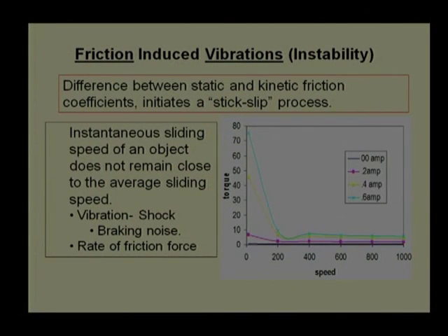To elaborate on this, I am showing a couple of results from experiments we have done on one brake material. We used a magnetorheological liquid as the brake material. The good thing about MR fluid is that it gets solidified in just a few milliseconds, and due to this solidification the coefficient of friction increases significantly. The coefficient of friction can go from 0.1 to 0.6 in 10 milliseconds, which gives a braking torque, or resistance against the movement.